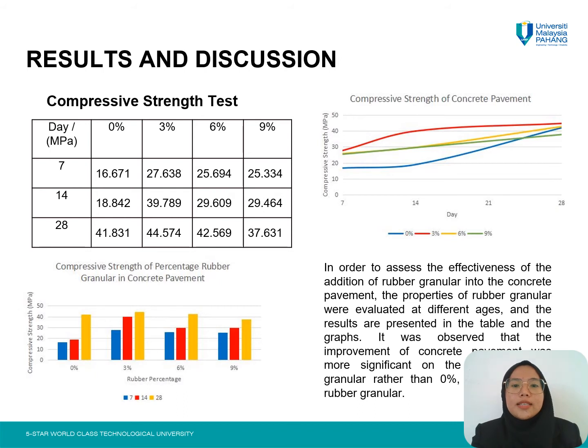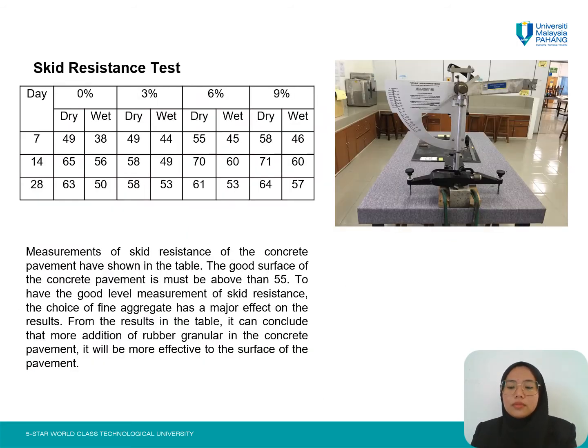Then this is the results and discussion. To assess the effectiveness of the addition of rubber granular into the concrete pavement, the properties of the rubber granular concrete were evaluated at different ages, and the results are presented in the table and the graph. It was observed that the improvement of concrete pavement was more significant at 3% rubber granular rather than 0%, 6% and 9% of rubber granular.